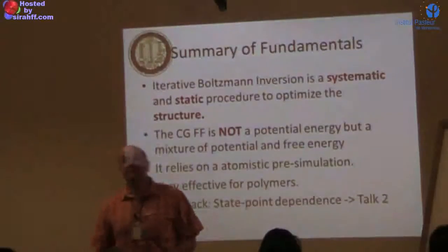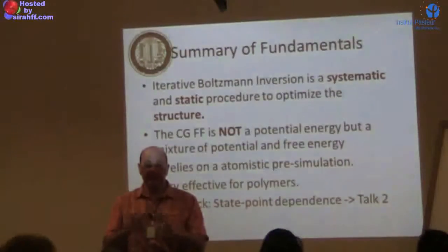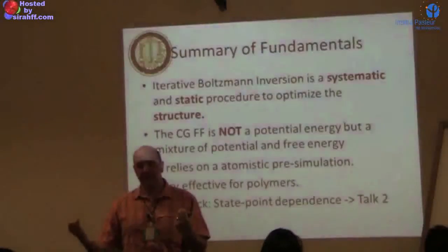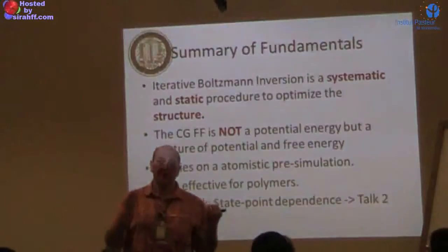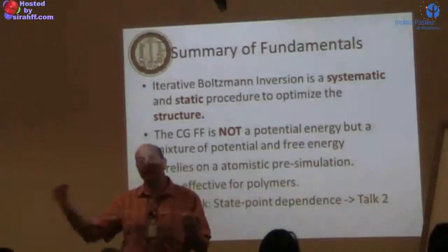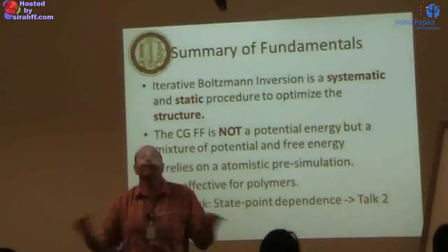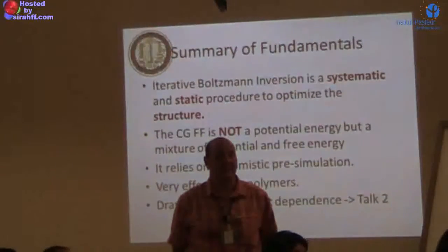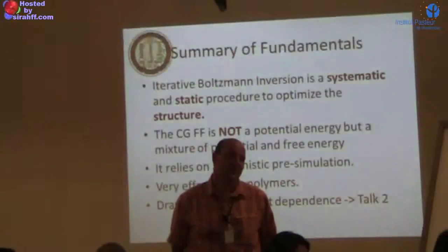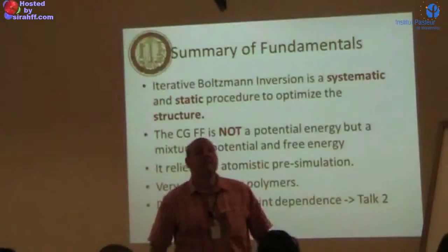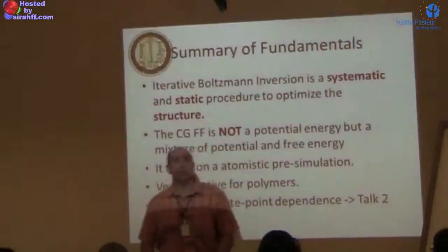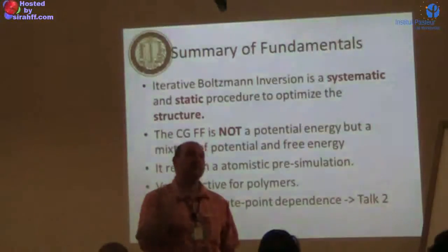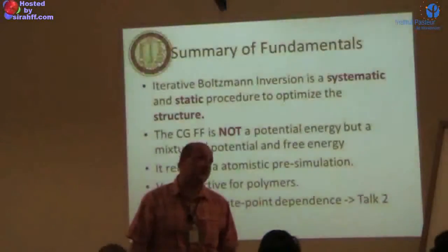You're very, very close. The main point is that we only got the relevant configurations at the state point in which we are. That means at other state points, other configurations are relevant, but we never sampled them in our atomistic simulation. So we never could fit against them, so we will never be able to do that. We are working on that. That is exactly where people are going, an explicit state point dependent potential. That's one of the areas where people are going.